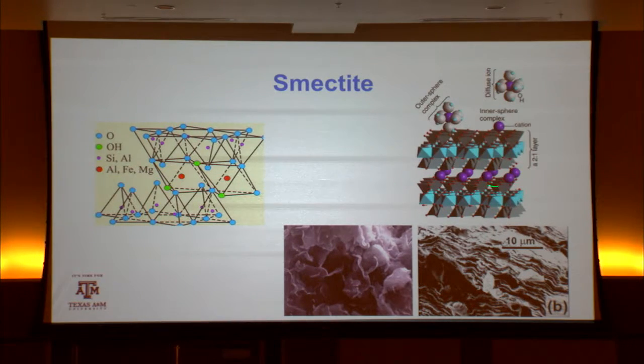Now, the size of that interstitial water layer is going to depend on the cation that's available. If I were to add Portland cement or lime to that clay system, the dominating cation would be calcium, which has two charges, two pluses to it. And calcium does not hydrate at the same level as sodium does, so it would suppress that water layer. It would reduce the shrink and swell characteristics of that clay because it's saturated with calcium instead of sodium, and give it a lower plasticity index, give it less potential to swell, give it less potential to shrink, improve its volumetric stability. So hopefully you can kind of glean that from this particular picture.